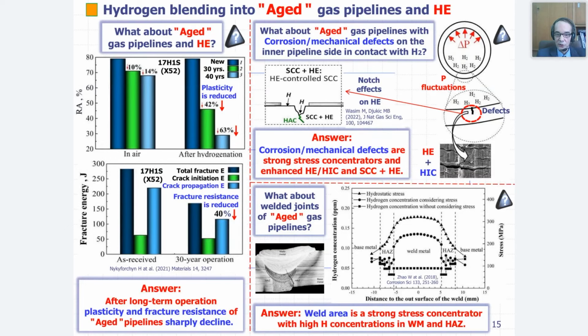The third question is, what about welded joints of aged gas pipeline? As you can see on the diagram, on the down right part of the slide, we have a very high hydrostatic stress in particular welding area, particularly in weld metal and heat-affected zone, which provokes the accumulation and high hydrogen concentration because of residual stresses and stresses in material. So we have a high hydrogen concentration in welded area.